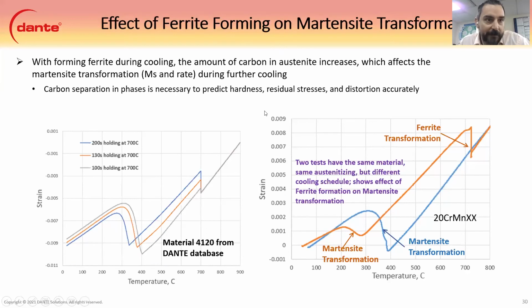Next, we have forming a ferrite. So this is carbon rejection we were talking about earlier. When we cool down here from austenite temperatures, we're all at the same temperature on the image to the left. And as we cool down, we do an isothermal hold at 100 seconds, 130 seconds, and 200 seconds. And the longer isothermal hold generates more ferrite, which rejects more carbon into the austenite matrix.